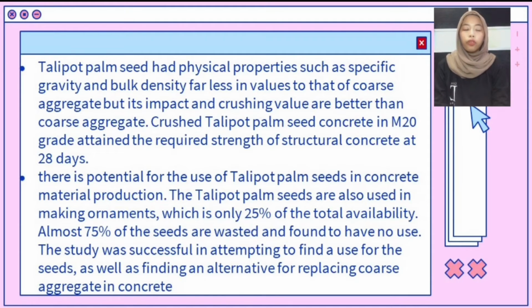Talipot palm seed had physical properties such as specific gravity and bulk density far less in value than that of coarse aggregate, but its impact and crushing value are better than coarse aggregate. Crushed Talipot palm seed concrete in M20 grade attained the required strength of structural concrete at 28 days.